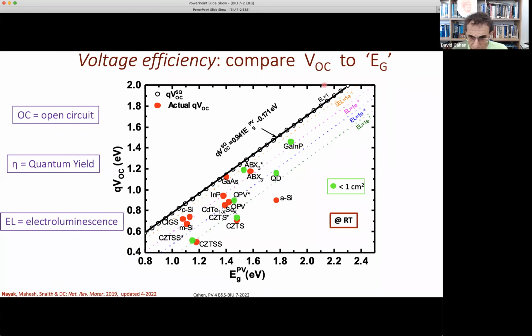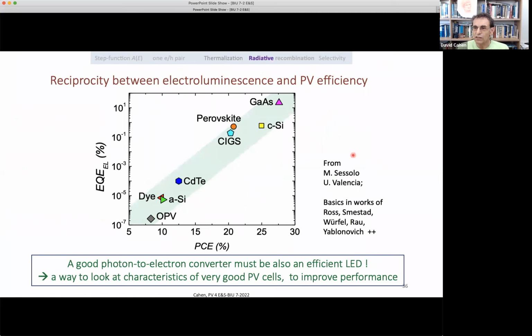By the way, this is logarithmic from 1 to 1/10, and then to 1/1,000. So you very quickly go to a situation where you can't measure the luminescence anymore. Therefore, it's not really true that a good solar cell is a good emitter. An excellent solar cell has to be an excellent emitter. And the moment it's not excellent, you shouldn't use this. So here's the reciprocity between the electroluminescence and the photoconversion efficiency, in general, between various types of solar cells. And here's the gallium arsenide, and the perovskite has gotten even a little bit higher since this plot was made.